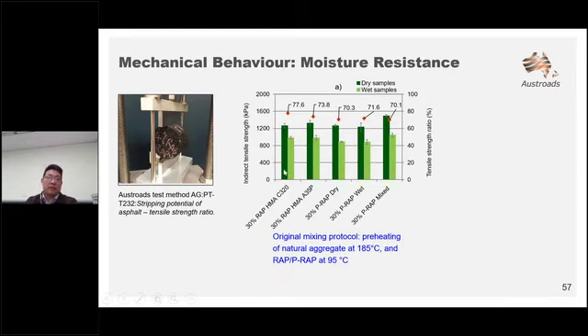So the next mechanical behavior investigation is moisture resistance. In general, the asphalt mixes with RAP and PRAP have a quite similar tensile strength ratio, ranging from 70 to 78%. It should be noted that the minimum requirement by the Australia and New Zealand standard is 80%. This result was obtained using the mixing protocol in which the natural aggregate was heated at 185 degrees and the RAP and PRAP was heated at 95 degrees Celsius.